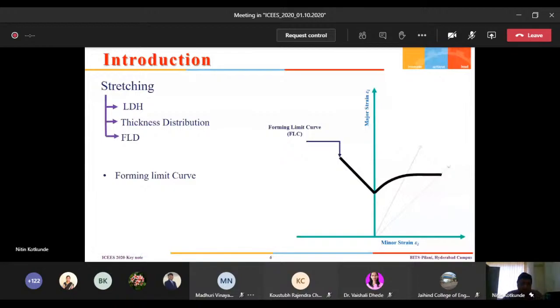From the researcher's or the industrial point of view, it is very essential to understand and analyze the FLC line exactly. The FLC line tells us how much we can form this material. Usually, if you stamp form a component, we should know what depth we can assure, without any substantial thickness reduction, cracking, or fracture, that we can form the component. So we study these different forming limit curves and how to plot them. Usually all the necking points are used to draw this forming limit curve.